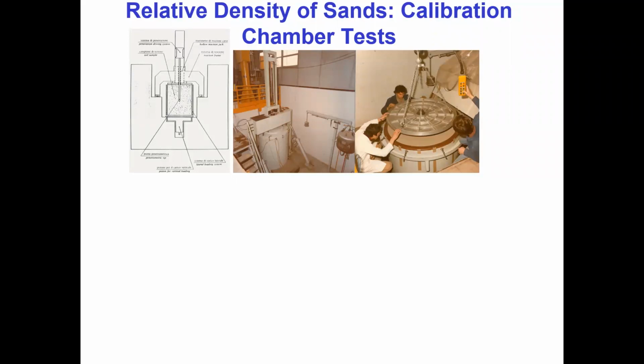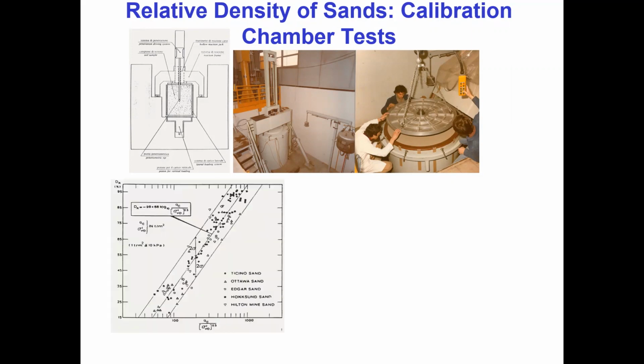Calibration chambers, you create essentially a large vat of sand at a controlled stress and relative density, and you push a penetrometer to measure the penetration resistance and correlate it from there. Huge multinational effort to make these correlations come about. And if you go back in time, the plot I'm most familiar with comes from a textbook by Renato Lancellotta in the early 1980s and looks like this. And what you'll see is the cone resistance correlated against relative density.